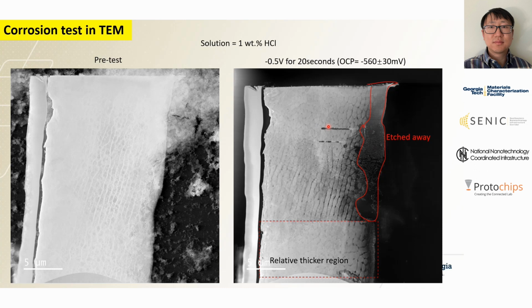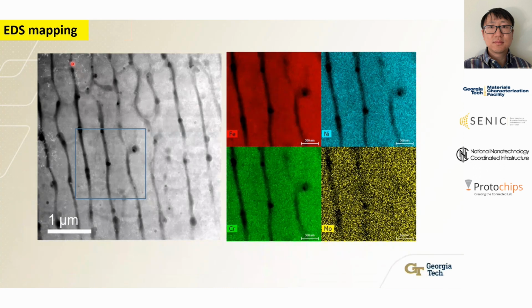If we zoom in, we can see the dislocation cell network gets corroded. And consistent results show in the EDS map that in all the elemental maps, the dislocation cell network shows a darker contrast, meaning the loss of material.